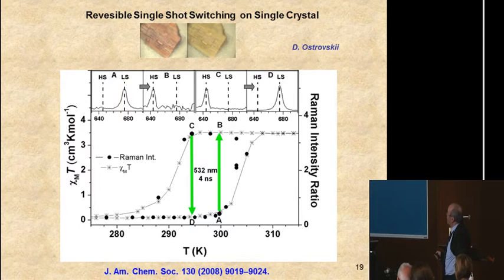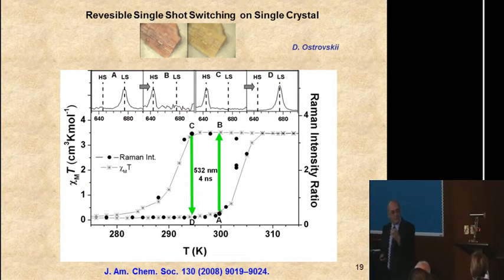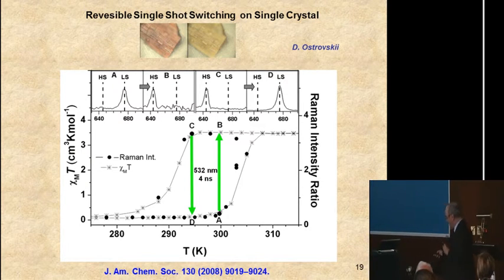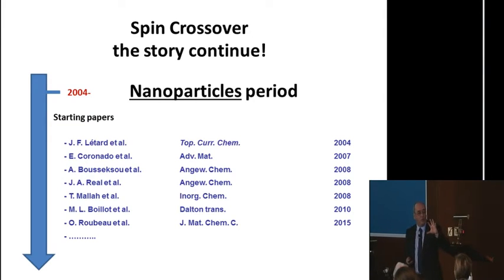That means that you go from completely high spin, like here, to completely low spin, so then you are going to here. So that means that with two pulses, two 4 nanosecond pulses, the first one you can go from the point A to B, you write your information from low spin to the high spin, from 0 to 1, and the second pulse you go from high spin to the low spin, you go from the state 1 to the state 0. This is the demonstration that at room temperature we can address these systems by using just two pulses, okay?